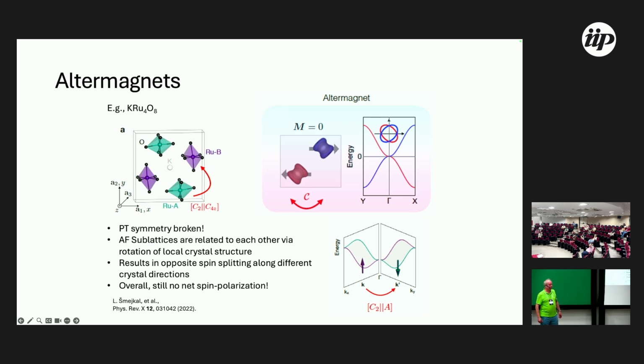Yeah, but then what's the difference between that and just a collinear antiferromagnet? If you take nickel oxide, for example, or cobalt oxide, which is just a collinear antiferromagnet, there the immediate chemical environment around the two sublattices is exactly identical. And so in those cases, cobalt oxide and nickel oxide will have spin degenerate bands for sure. Okay, that's the difference.